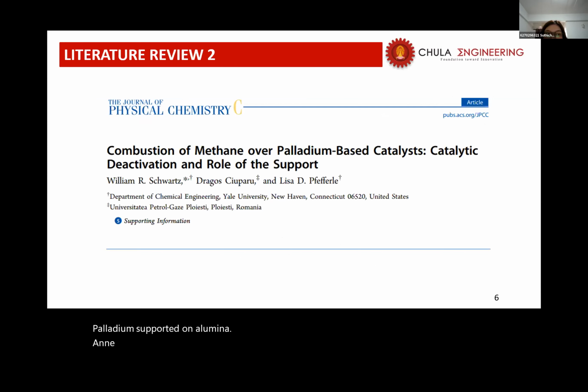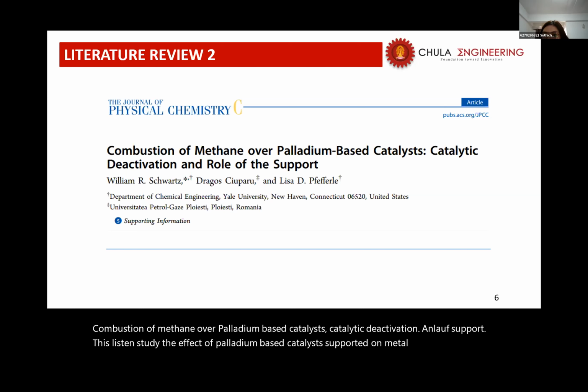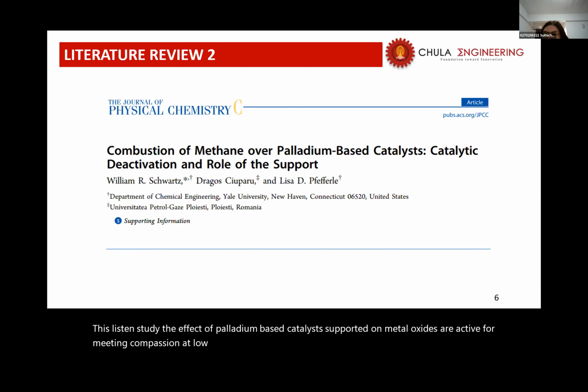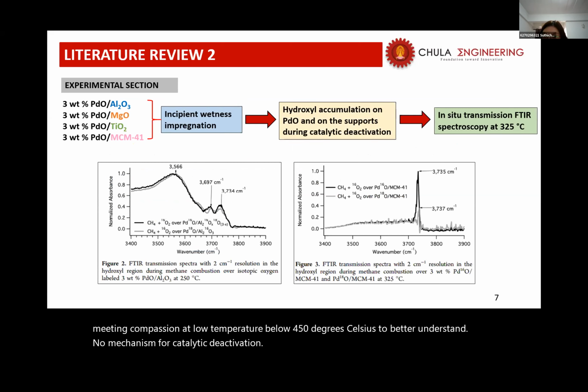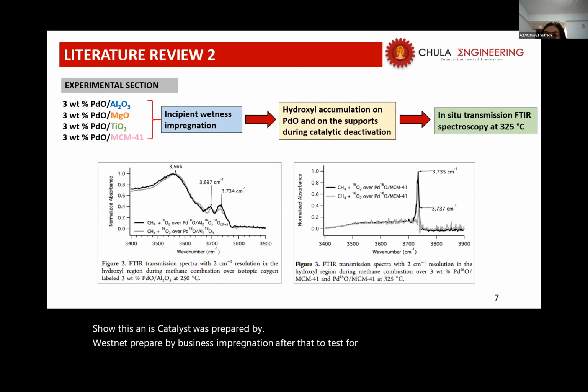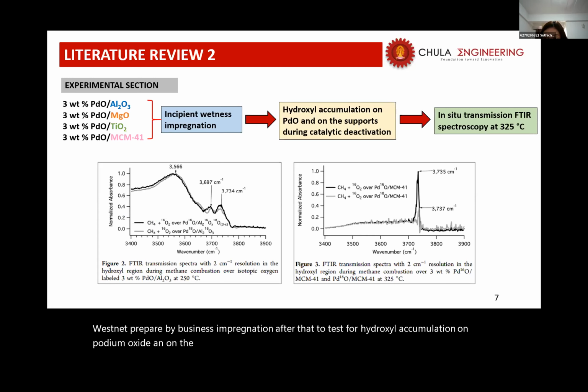And next research. This research topic is combustion of methane over palladium-based catalyst, catalytic deactivation, and role of support. This research studied palladium-based catalysts supported on metal oxide, which are effective for methane combustion at low temperature, below 450 degrees Celsius, to better understand the mechanism for catalytic deactivation. Catalysts used in this investigation were on 4 supports. The catalyst was prepared by wet impregnation, and after that tested for hydroxyl accumulation on palladium oxide and on the support during catalytic deactivation. They utilized in situ transmission FTIR spectroscopy at